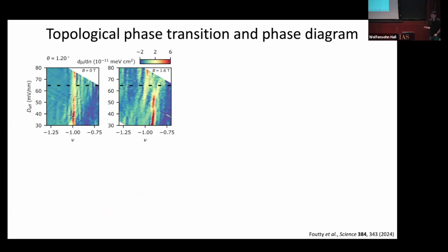So in a magnetic field, a trivial state and a topological state will occur at different densities. So we can do the same sort of measurement now at 1.6 Tesla, where in this low displacement field limit, you can see the incompressible state is offset from nu equals 1. That's a sign that it's sloped in a magnetic field, that it's a quantum anomalous Hall state. Whereas in this high displacement field limit, you can see that the state is pegged right at nu equals 1. So again, at the same effective critical displacement field, you get a transition in where the incompressible behavior occurs. So this also is very suggestive.